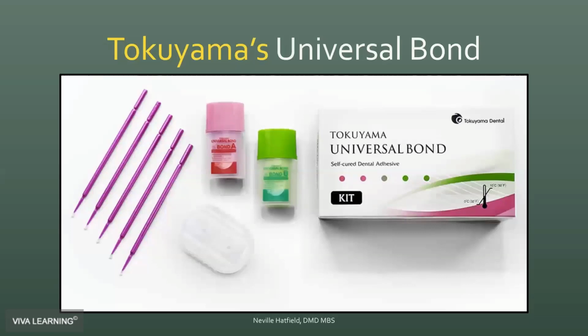You apply it to the intaglio of your restoration if you're using an indirect restoration, or if you're doing a direct restoration like a resin composite in the posterior, you can scrub it right into the dentin right after that. All you need to do after that is air thin it for 5 seconds on light air and then 5 seconds on medium air, and then you are ready to go. There's no light curing needed, so that saves you anywhere from 10 to 20 seconds.